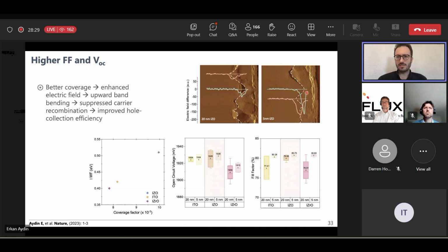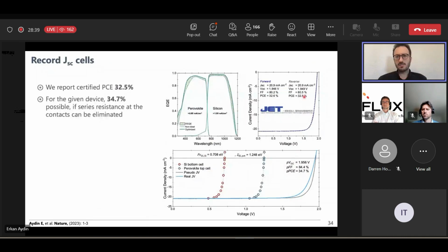And we had a chance to enhance the electric field because of the enhanced SAM coverage, and also a better homogeneity at the interfaces. So basically, this device ended up, adding all these improvements, with 32.5% certified efficiency, and this device also had a potential to reach an efficiency level around 34.7%. These are calculated values from the PL and EL measurements. We constructed the JV curve, and this JV curve is showing the potential of the cell if the series resistance at the contacts can be eliminated. So transport losses are eliminated.